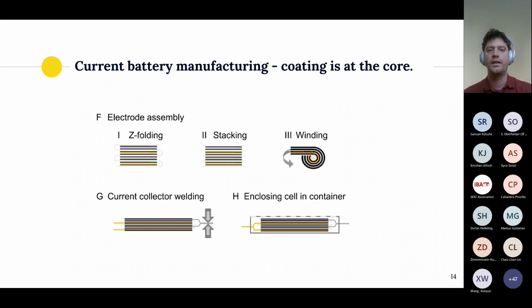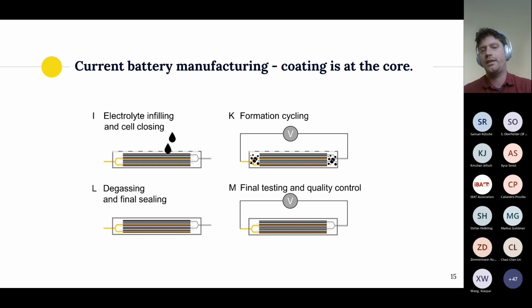Again, here, depending on the format, there are different ways to do so, either through a Z-folding process where the separator is weaved in between cathode and anode alternating, or you can do a discrete stacking process or winding as you wish for your final cell format. Then obviously you need to combine the current collectors by welding the tabs together, enclose it into a container, and you're almost done. But then you need to infill the electrolyte, the liquid electrolyte, before closing the cell. And this is typically done with a vacuum process.